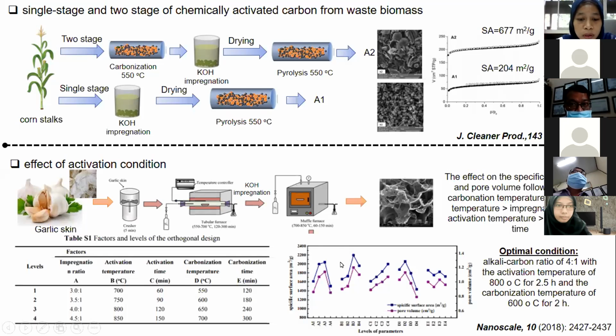So the garlic skin powder was pre-carbonized first under nitrogen at various temperatures, and then mixed with KOH and heat treated under pure nitrogen at various temperatures. The chemical activation process was conducted with these various conditions. You can see these various conditions. And using that, there are parameters that affect the surface area and pore volume of the carbon.